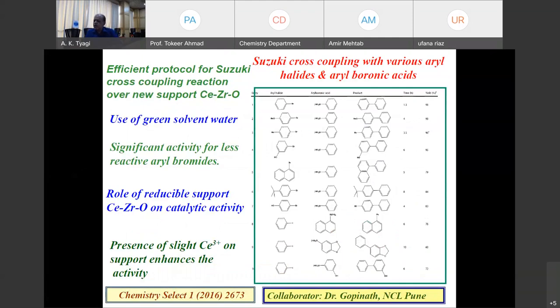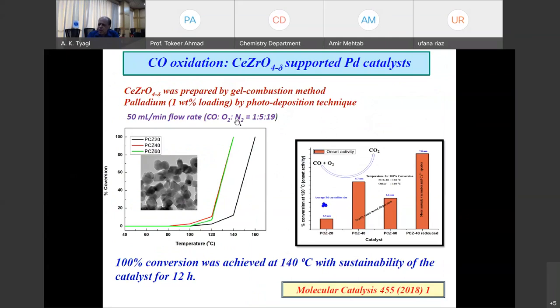So again, you see, in this work, this compound turned out to be an excellent catalyst because here nano attributes were coupled with crystallographic attributes. So together, when you use the best of both, you get this kind of interesting materials. So I move forward. This compound was also used for oxidation of carbon monoxide to carbon dioxide.